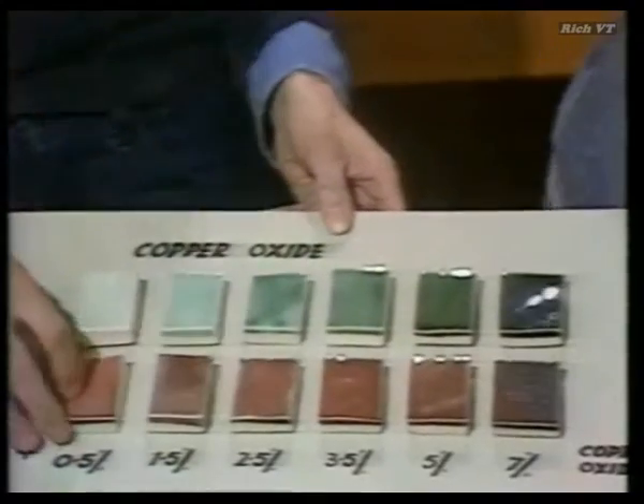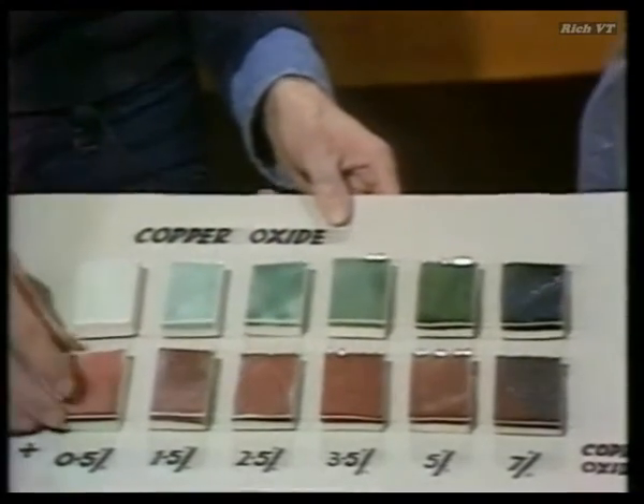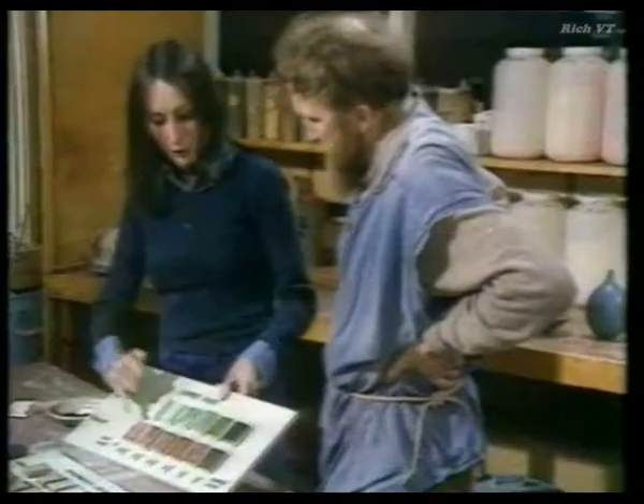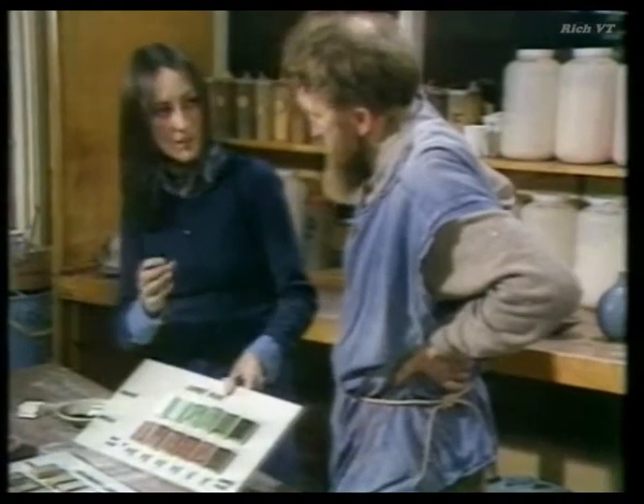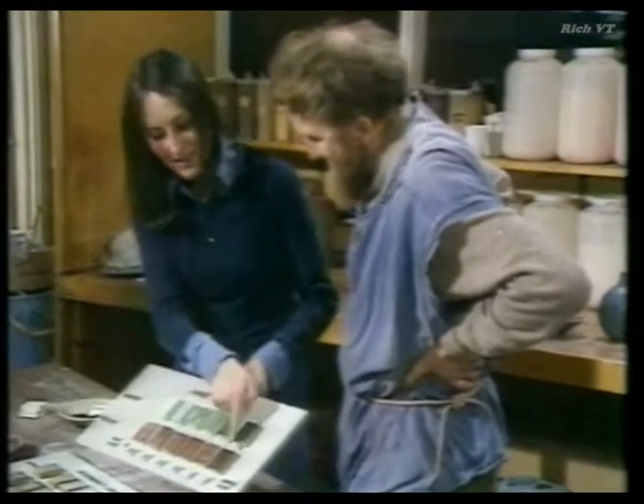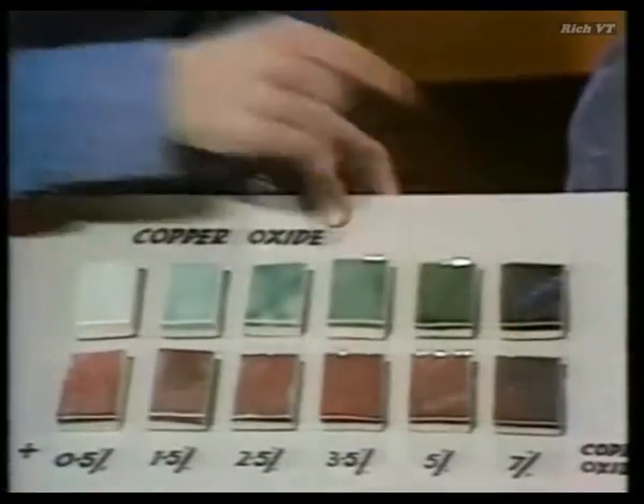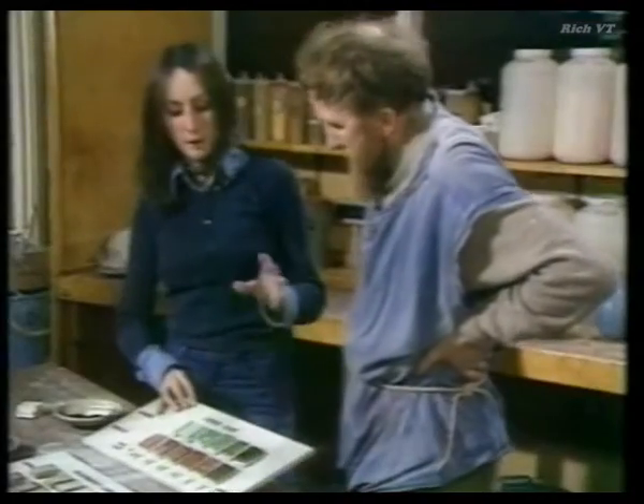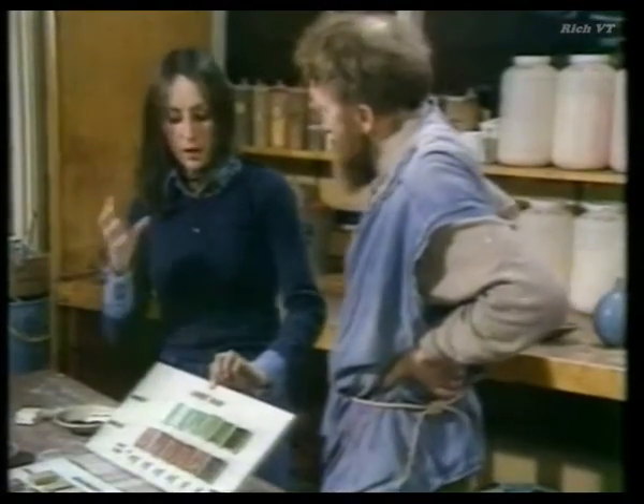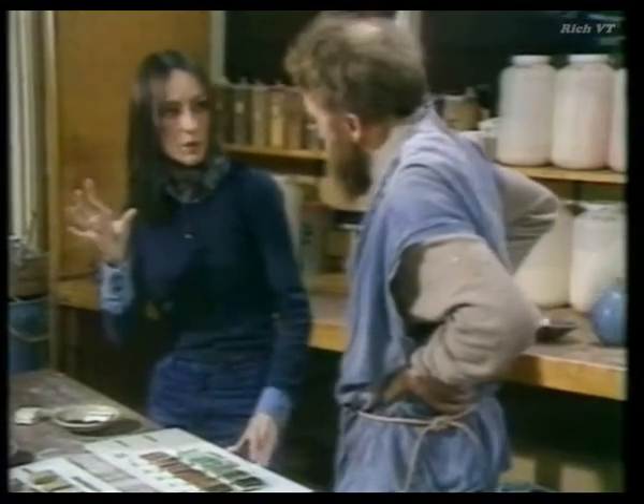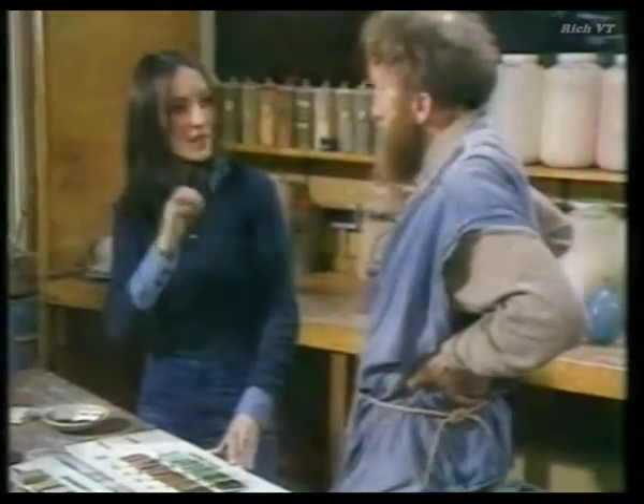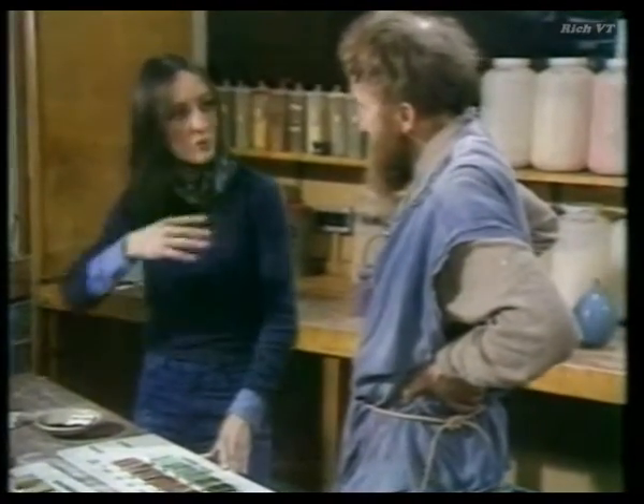Now, these pinks and reds in reduction are rather difficult because they're unstable, and you might find sometimes that the red you want comes out rather tinged with green, as in the case of this one. It's a very dramatic oxide. It certainly is, and in fact sometimes if you put a copper-coloured pot into a kiln, the surrounding pots can come out tinted with the copper colour. It seems to spread all around the firing.